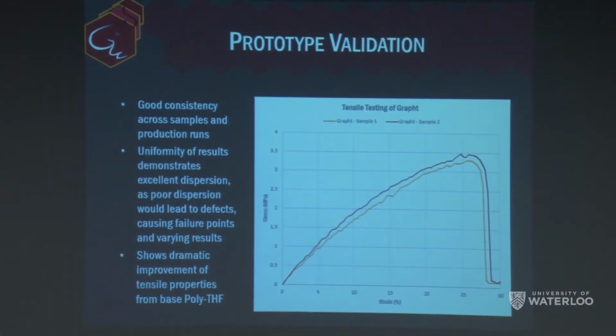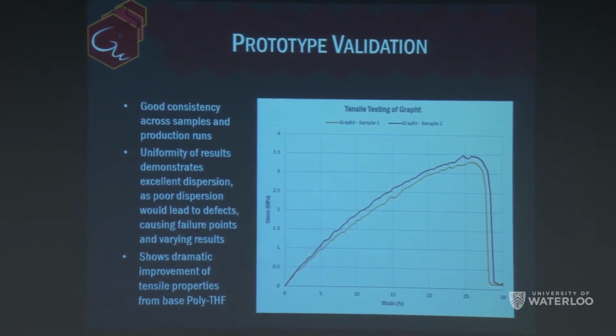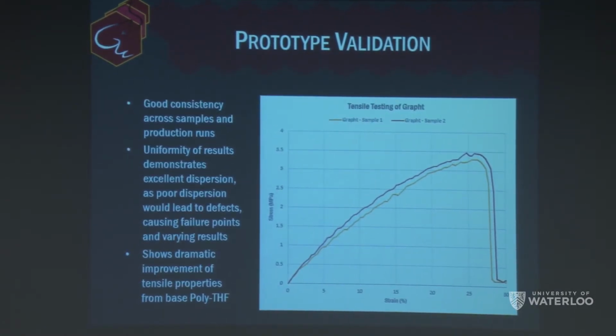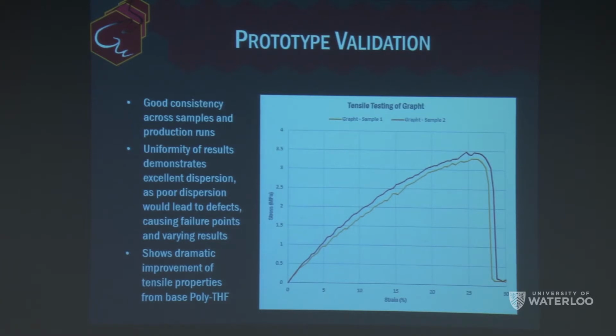And lastly, we have CH bonds at 2 peaks, which are very large after the addition of the graphene, the linkage of the graphene to the poly-THF, and this indicates that the graphene was well added to the mixture. We also tested the tensile properties of Grapht, not necessarily for the material properties of the additive itself, because frankly they're not that great, because there's short chain lengths and you don't really have that much entanglement. However, this test has managed to show that inter-batch variability is low. Our material properties between the multiple batches are nearly identical, which shows that our procedure works, it works repeatably, and we can do it multiple times.